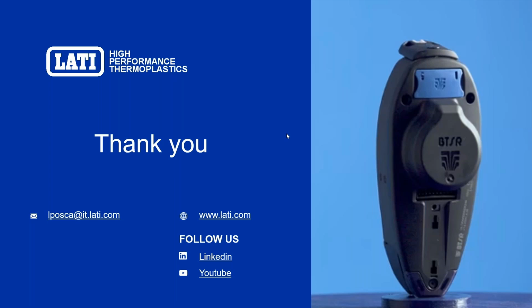Have you checked if injection point location has an impact on performance? No, actually we didn't, because we were supposed to injection mold plates, and plates are injected on the side with a large fan gate, creating a more or less high, uniform orientation. But your question is very interesting, because injection location can affect fiber orientation and networking quite a lot. So also in this case, it would be interesting to measure if something changes.